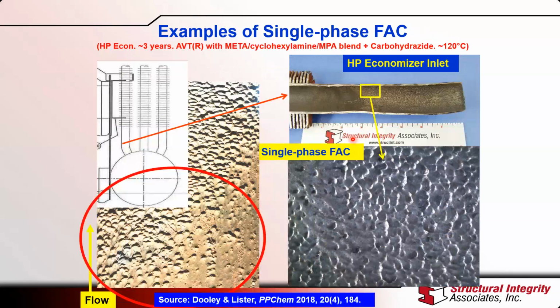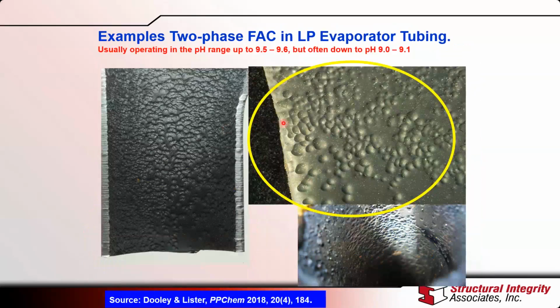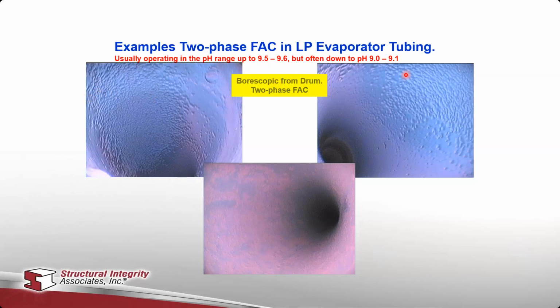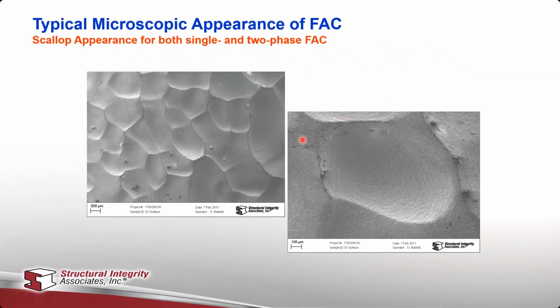You typically just go back to this one. You see this orange peel type of appearance, and for two phase you see this black shiny appearance. And this shows, using a borescope from the drum looking down at LP evaporator tubing, this two-phase black shiny appearance of the FAC. And if you look at these surfaces in detail under a high power microscope, a scanning electron microscope, you'll see this appearance. And this is what we call the scallops of FAC. You have to be able to see this appearance at the higher magnification to confirm that the mechanism is FAC. This is a very characteristic scallop appearance that occurs for both single and two-phase FAC.